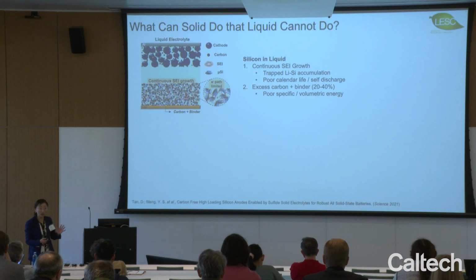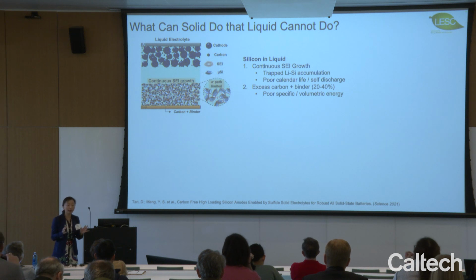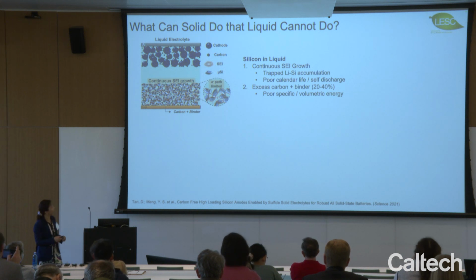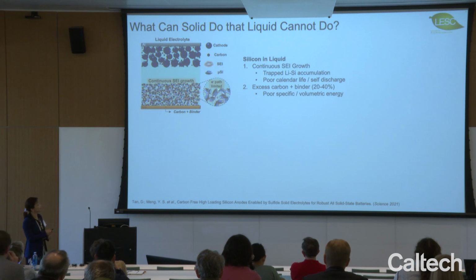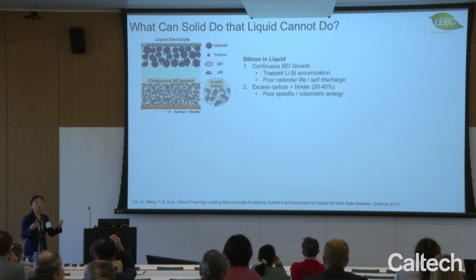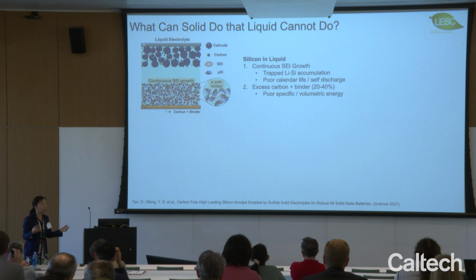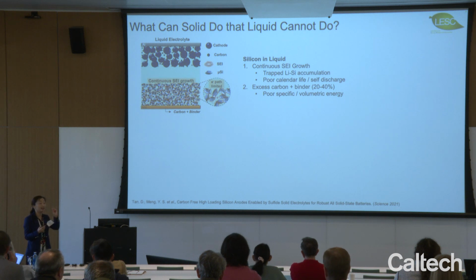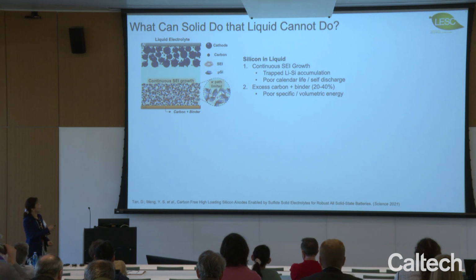So I'll just say one story about where we truly demonstrate solid state is unique. Okay, so there is an anode material called silicon. In fact, silicon is a favorable topic for many battery researchers since 2006, because each silicon can take up to 4 lithium. So its energy density is at least 10 times higher than that of the graphite, the one currently used in our cell phone. Now, people make a very sophisticated nanostructure of silicon to combine with the carbon and the binders, and then they put in the liquid.